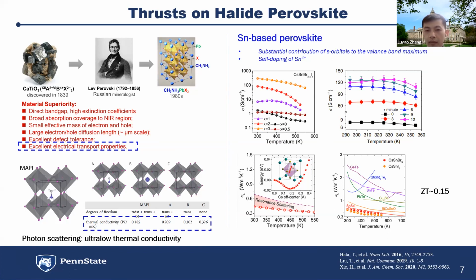So people are now looking for some perovskite, like tin-based perovskite, because this tin atom will contribute more to the valence band because of the s orbitals. It will give us even better electrical conductivity. This is good compared to the lead-based. And also the divalent tin is easy to be oxidized to the tetravalent, inducing some self-doping.